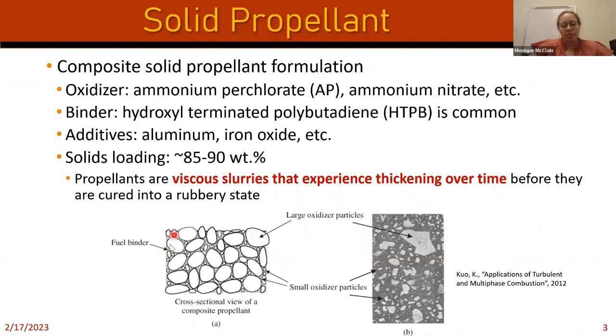Beyond that, the polymer that holds everything together is typically some sort of viscous resin system. A common binder that we use is called HTPB, or hydroxyl-terminated polybutadiene, and it's a polymer that can be cross-linked thermally over time. So typically you mix it with some isocyanate, and then you put it in an oven at elevated temperature to help it cure within maybe a few days or up to a week, depending on what kind of ratio you have there.